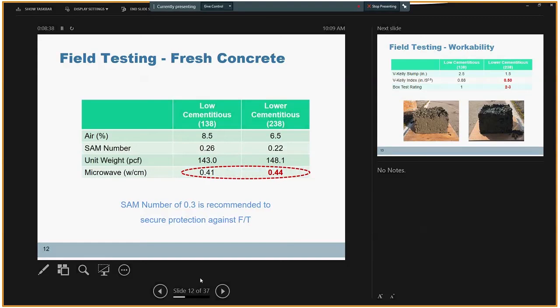So starting with the fresh concrete properties, for the investigated mixtures, both low and lower cementitious material, we had a proper air void system in fresh concrete. We had 6.5 and 8.5% air content in the fresh state, and we had SAM numbers of 0.22 and 0.26 for these two concrete mixtures.